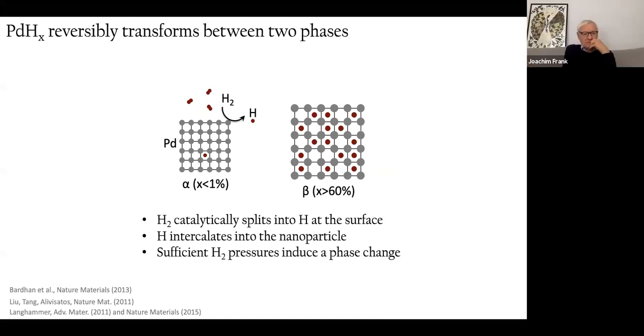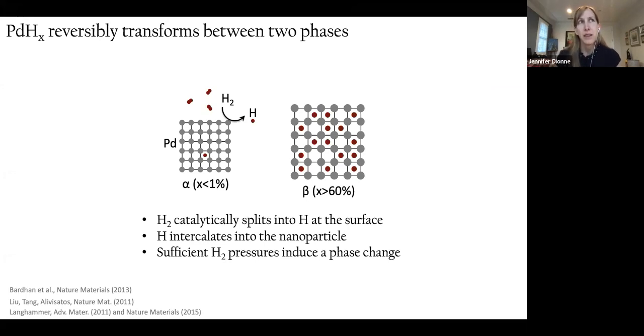At sufficient hydrogen pressures, you're going to have a phase change. So at low enough pressures, there's not really a lot of hydrogen that's intercalated. Once you've gotten to high enough pressures, you're going to have a phase change from the alpha phase to the beta phase. That phase change is accompanied by a lattice expansion. And I'll mention that this not only occurs in bulk, but can also occur at the surface. And I'll share with you how we can probe that subsurface formation. That phase change is associated with about a 10% lattice expansion in volume, or about a 3% change in lattice constant.